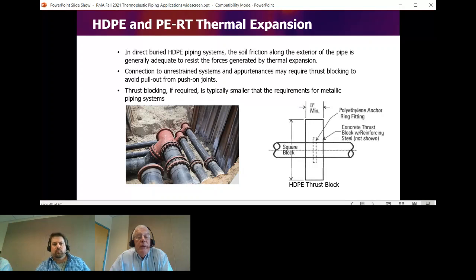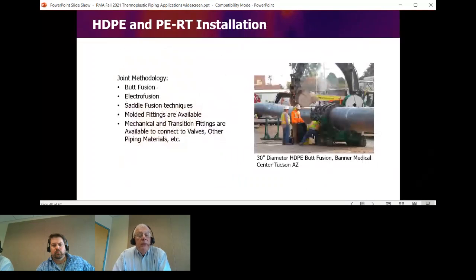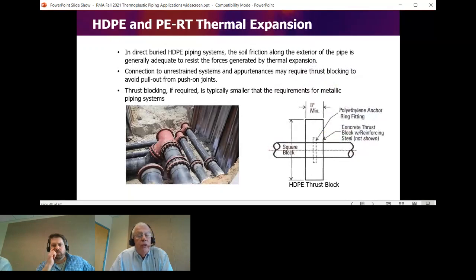Typically, along HDPE pipe, you can use the soil friction to restrain some of the force that is developed during expansion. Connections can be made with either fully butt welded fittings all the way through, or a combination of fittings and mechanical style joints that are restrained to allow you to handle the connections. Basically, you make the majority of the dips or crossovers up on top of the trench and either connect with couplings on either side or use ductile iron fittings as required. Typically, there's no requirement for thrust restraint.